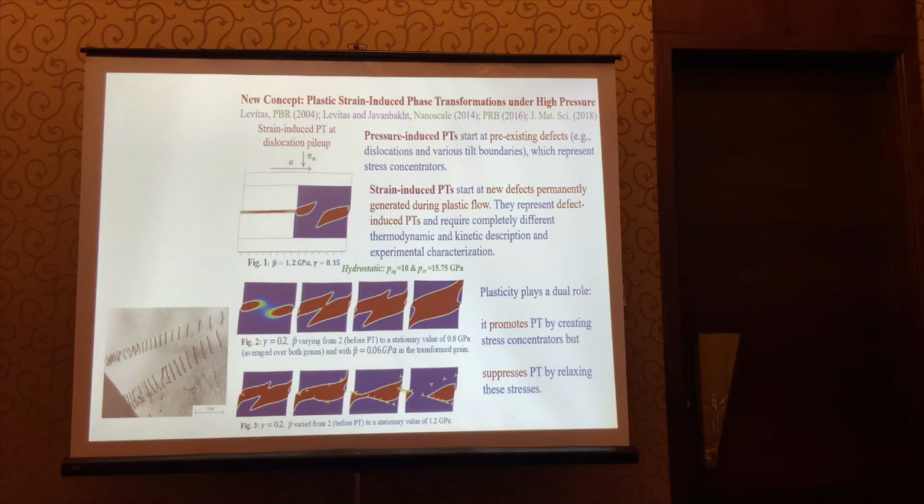We develop a phase field approach, a nanoscale phase field approach, consistent with atomistic simulation. First for phase transition, then for dislocation, then combine. And let's consider a model problem for a material with phase equilibrium pressure of 10 GPa. If you introduce one dislocation, the phase transformation pressure under hydrostatic condition is 16 GPa.